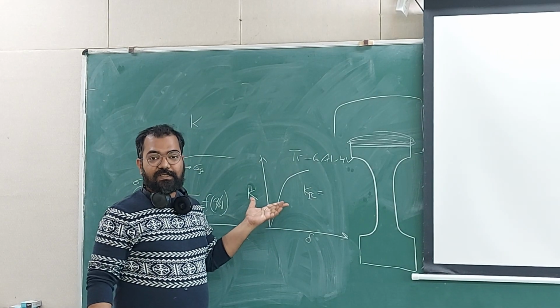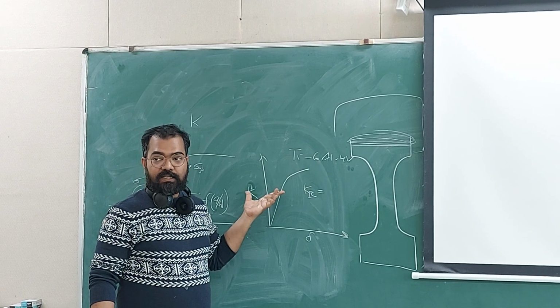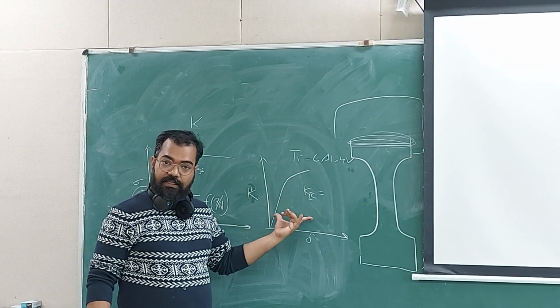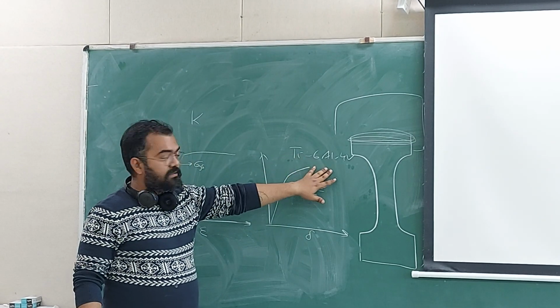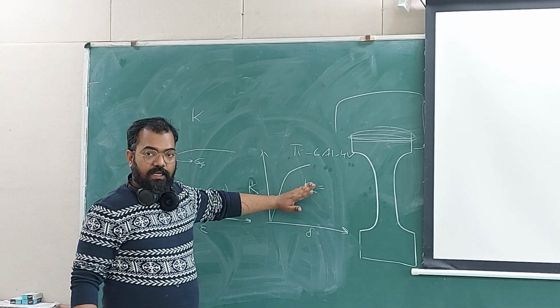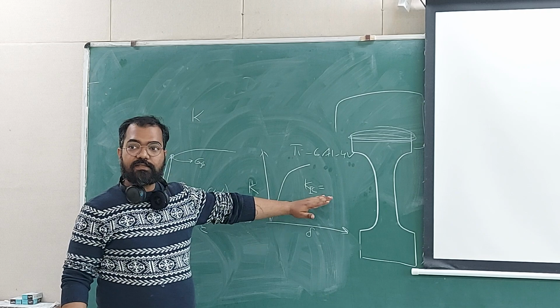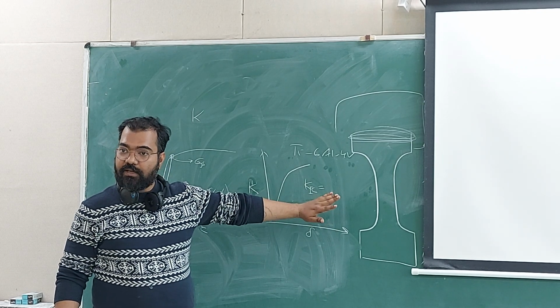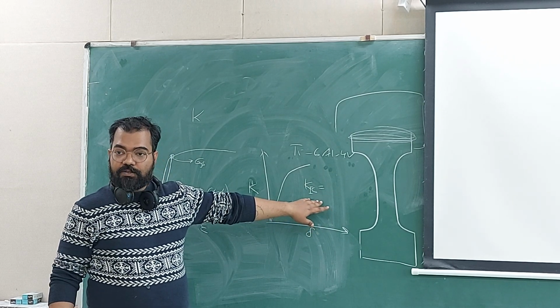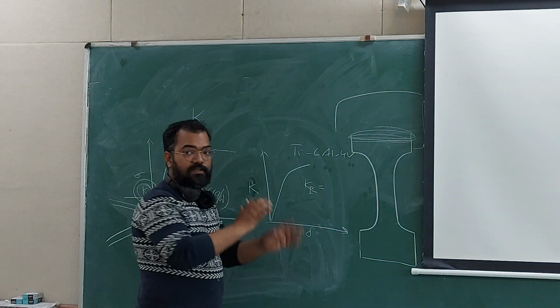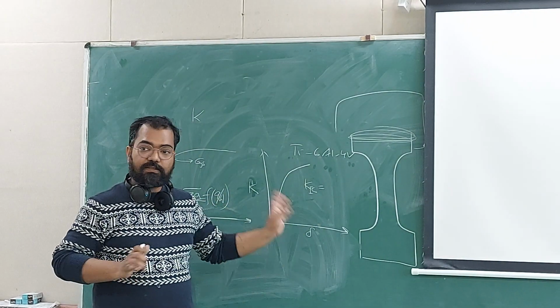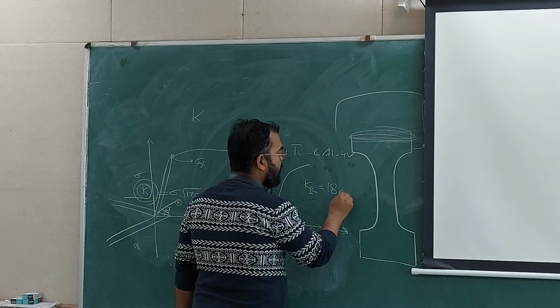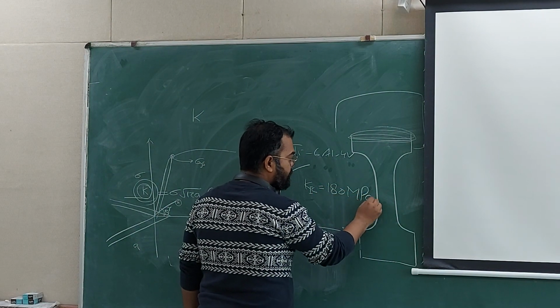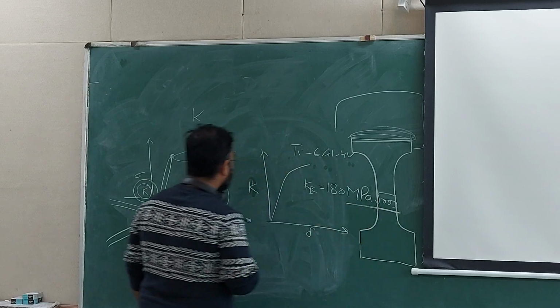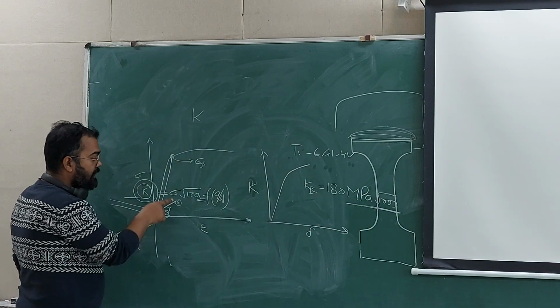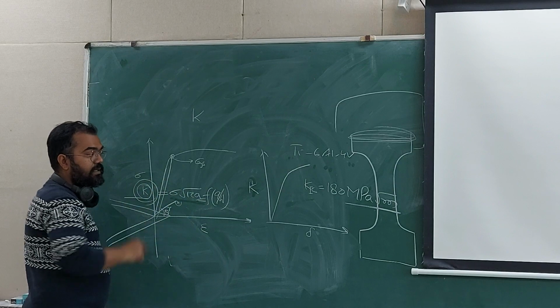K1c. Mode 1 is the worst condition, and in that condition, for a crack length in this alloy, you do the testing and find out when the crack started propagating, and that value is K1c. Somebody has done the test and told me the value of K1c, let us say 180 MPa root meter. MPa root meter is the unit of K1c.